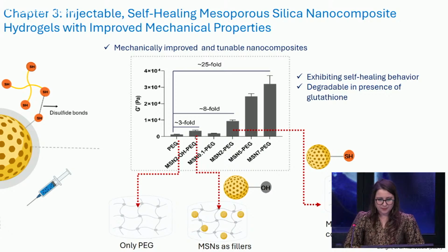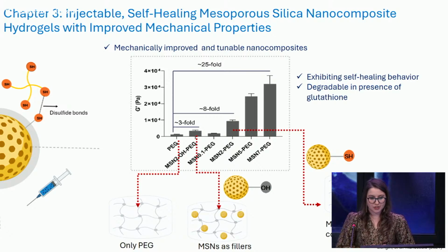So in chapter 3, I developed nanocomposite hydrogels by cross-linking thiol-functionalized MSNs with thiol-functionalized PEG through thiol-disulfide exchange reactions. This approach stands out because, unlike the common use of MSNs as filler components, where they simply remain passive and encapsulated within the hydrogel, our MSNs actively contribute to the hydrogel network formation by forming disulfide bonds with the PEG backbone.